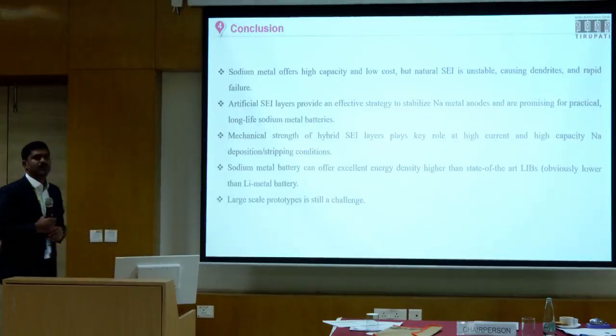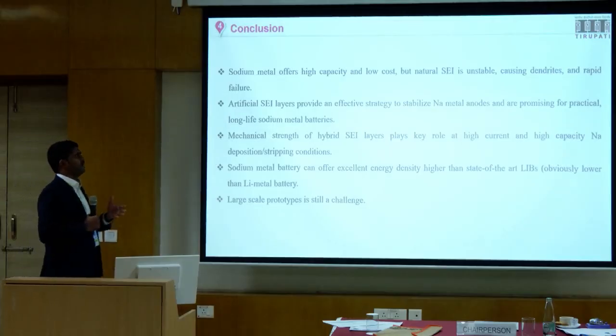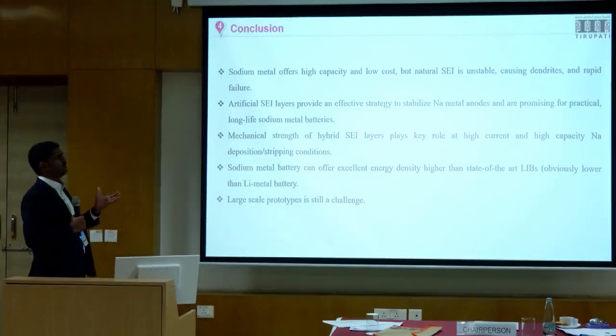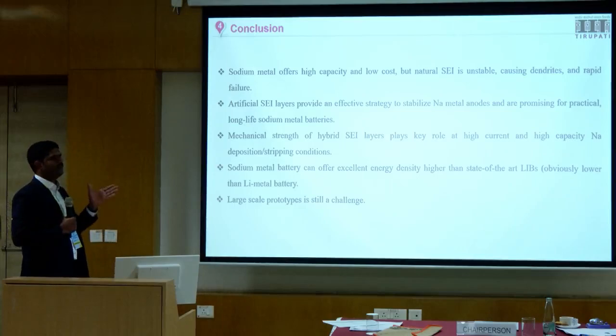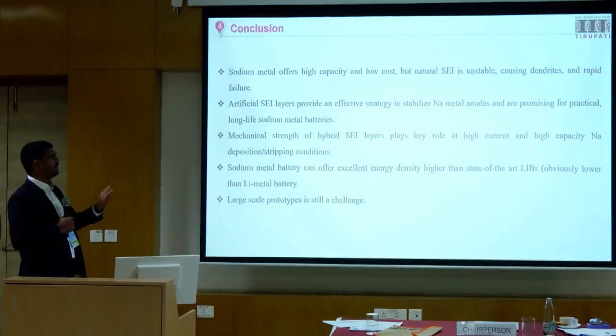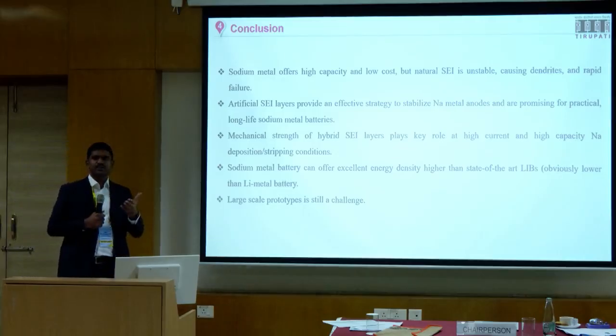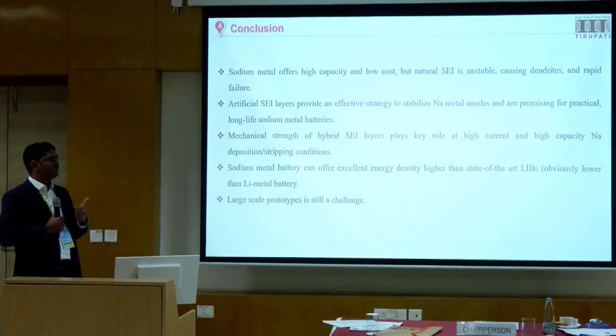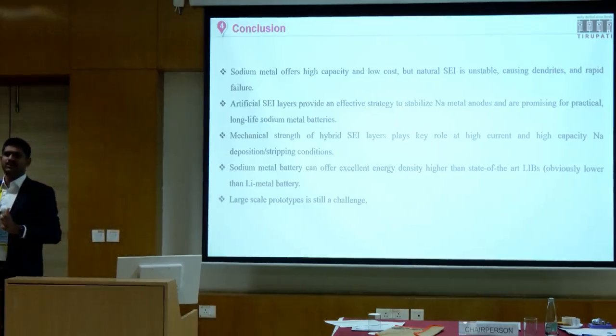Okay, so these are the conclusions from my presentation. Obviously, sodium metal really offers high capacity and it's low cost, but obviously the natural SEI layer has its problems, and they can be addressed by developing artificial SEI layers based on alloy type or solid electrolyte type SEI layers on the anodes. So next generation sodium metal based batteries can offer really high energy density compared to state of the art lithium-ion batteries, but obviously the energy density will be lower than lithium metal batteries. Large scale prototypes are still challenging because developing large sized batteries with metal anodes needs a lot of engineering, which we are trying to address through the ongoing EV Mission Mode project. So thank you.